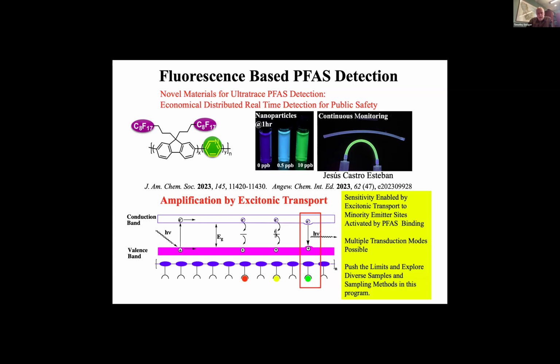The reason we gain such high sensitivity in these materials is that the polymer we show up here is electronically delocalized. These double bonds are what we call a pi orbital system, which creates a semiconductive structure where we have a filled band of energy levels called the valence band and an empty band called the conduction band. When a photon promotes an electron from the valence band to the conduction band, the two carriers, the electron and hole, are coupled, and they move together as a quasi-particle that we call an exciton. If it runs into a low band gap site or other places in the polymer that can do electron transfer, but in this case, if it runs into a place where an analyte, for example a PFAS, binds, it will create a site-selective luminescence from that place.